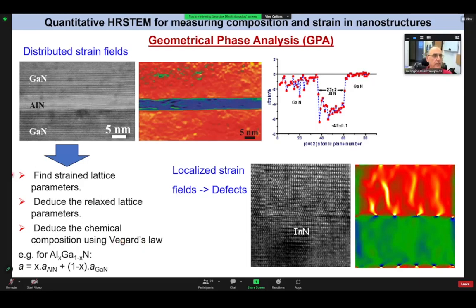We have, let us say, a reference lattice, like here gallium nitride. This lattice changes. For example, here it becomes aluminum nitride. So what you do is that you map this change with respect to the reference area, which is gallium nitride. So you can measure, having as reference, your gallium nitride. And then you find how much your lattice parameters change, and by this measurement of the lattice parameters, you can determine the composition that corresponds to these lattice parameters. So this is a structural way of determining the change in the composition.